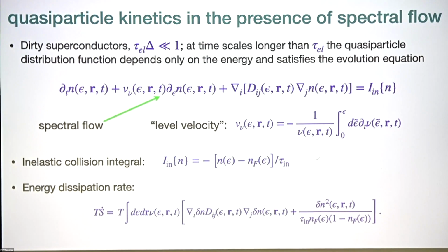And the second important thing is this contribution of the spectral flow. So the diffusion is elastic, it conserves the energy, but then because of the spectral flow, quasi-particles can be deposited to a given energy from other energies. And so this is the term which will play the main role. And here, V sub nu is what we call the level velocity. It has units of 1 over time. And it can be expressed in terms of the time derivative of the local integrated density of states here.